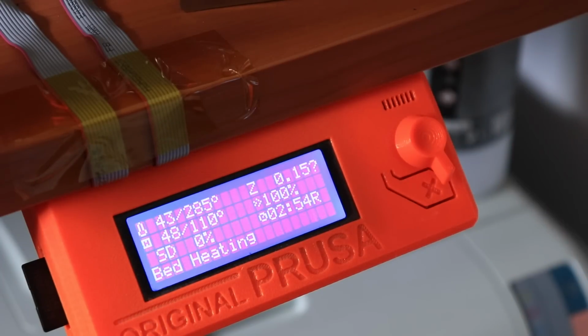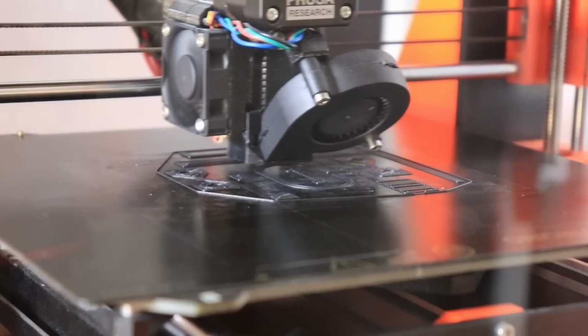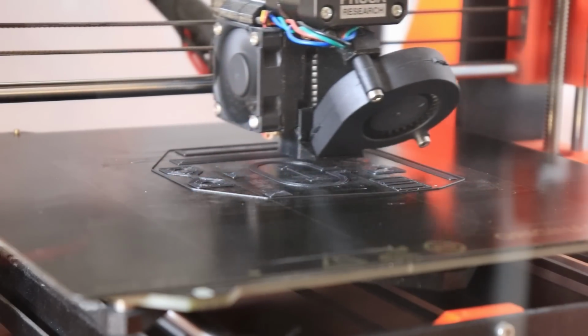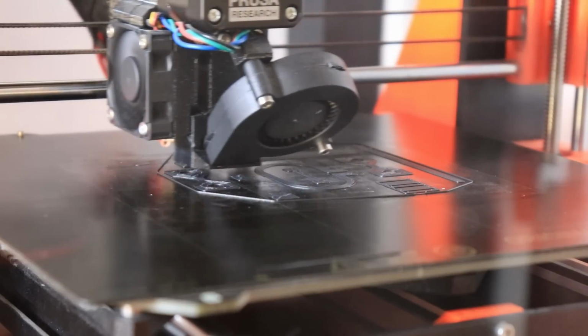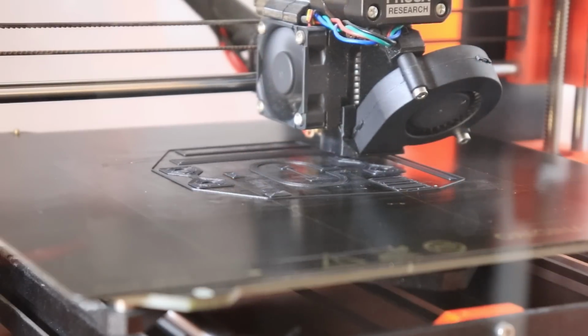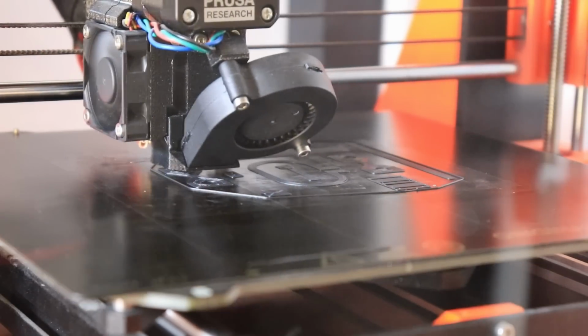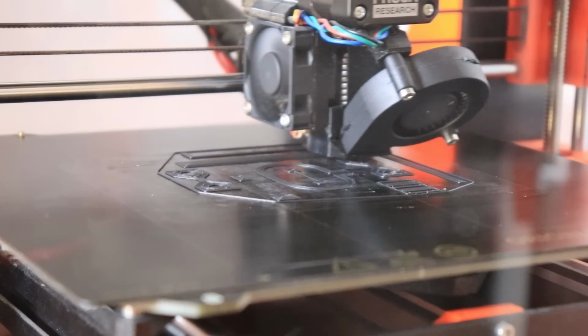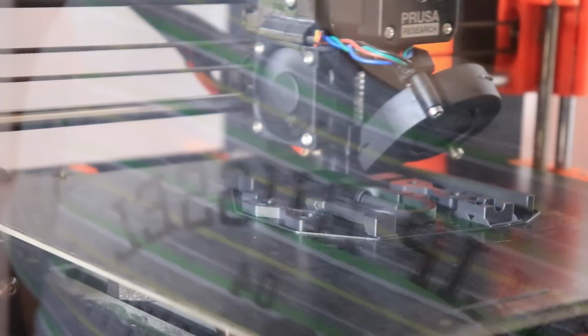And I will print test objects without brim as a first attempt. The first layer laid down perfectly, and I will try to print this without brim, and it will be a successful print. In that case, this is easier for printing than a regular PC blend. And after 1 hour, still perfect printing without any signs of warping. And only 1 hour of printing left, and I hope everything will be okay with the mechanical testing, because this may easily become my new favorite filament.